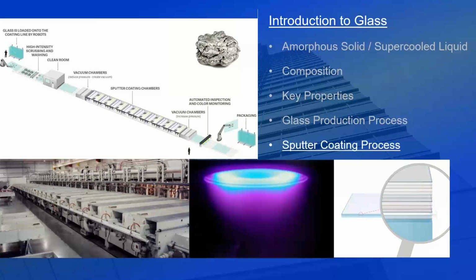And we go from standard Earth atmosphere, roughly sea level atmosphere, to a very, very low pressure, mostly argon atmosphere. In the sputter coat chambers, each pair of cylinders or each pair of plates represents a different metal layer on the Low-E coating. Those cylinders or plates get enveloped in a plasma, roughly visualized by that middle lower image there. And so each layer or each pair of plates or cylinders that the glass passes under deposit an additional layer of metal onto the top of that glass.